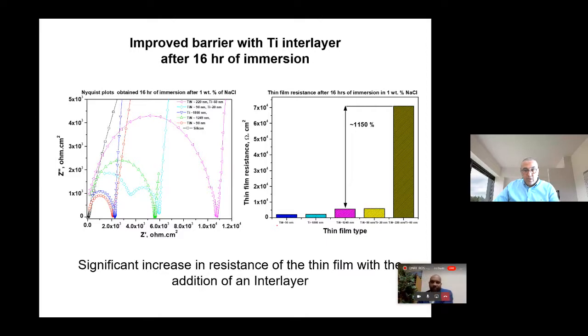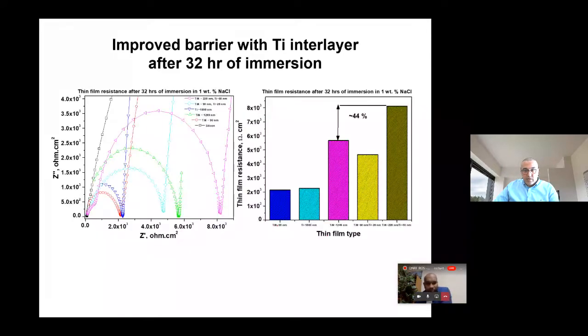And when we extended this study and continued for about 32 hours or so, you could start to see that the titanium nitride and the interlayer differences become a lot more comparable. However, again, with the caveat that there were some defects that we saw in our material.